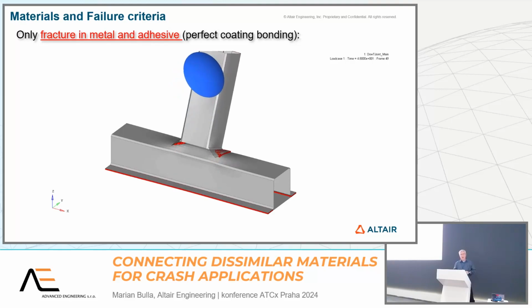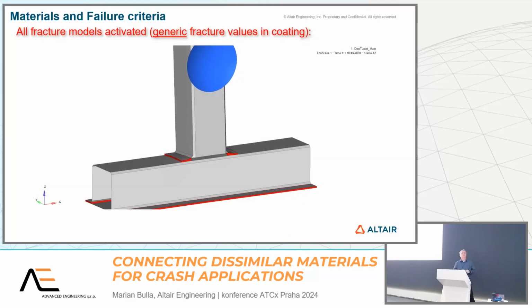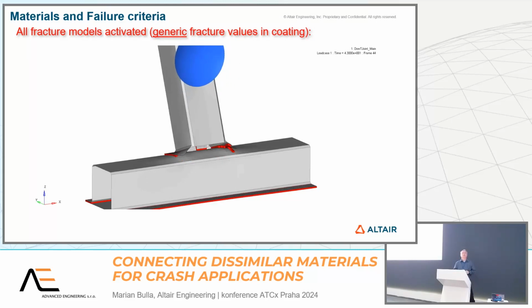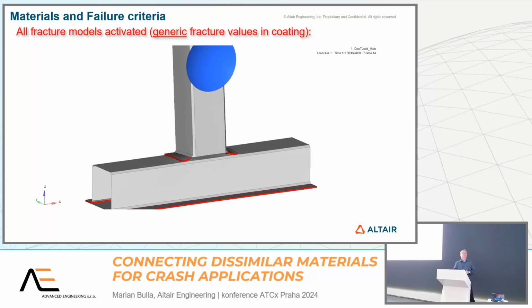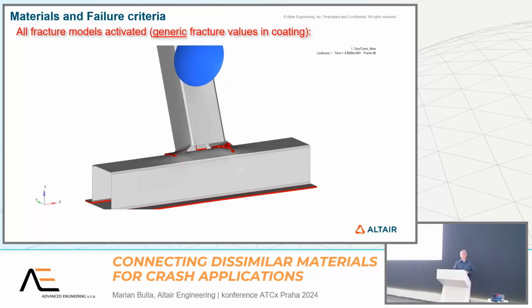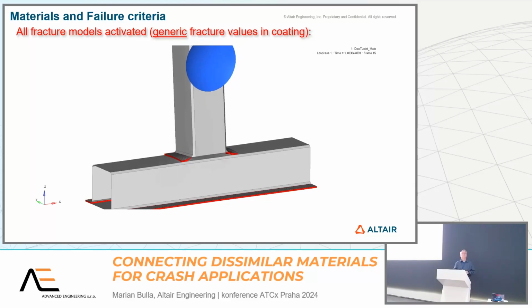And now let's apply also fracture in the coating. And now I can see some elements are still not broken for the adhesive, which means the bonding has failed. The contact interface, the tied interface failed, and I see the adhesive is still gluing on this part or here, which means the failure occurred in the paint.